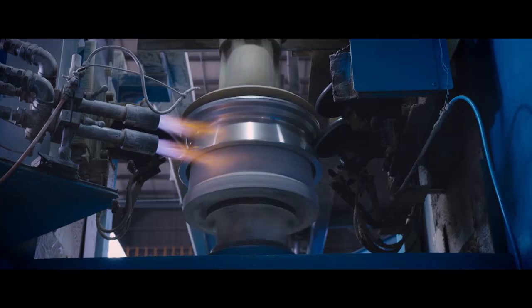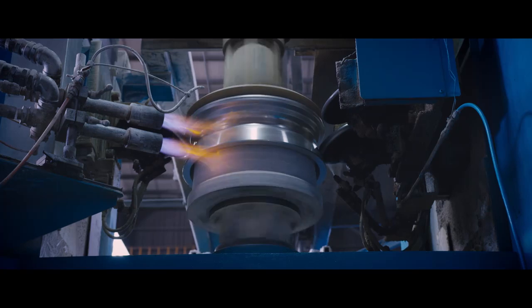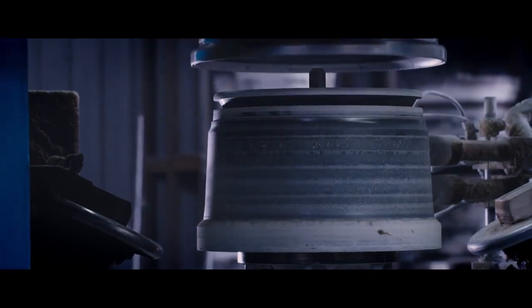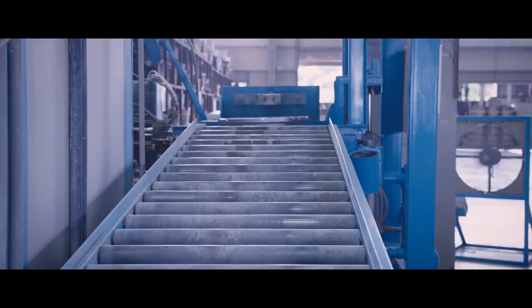The rollers slowly squeeze the aluminum skirt into the final rim barrel shape along the mandrel's sides. It will take multiple passes of the rollers to move all the skirt material into its final rim barrel shape. The wheels are again quenched to ensure the mechanical properties are maintained and to minimize distortion.